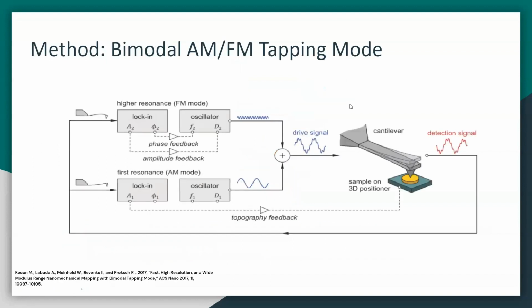So the actual method that I use for the AFM is called bimodal AM/FM tapping mode. And this is shown in the schematic here. It's a fast force mapping mode within the AFM where two resonances are driven at the same time. The first is the higher resonance FM mode, and then the second is the first resonance AM mode. So the topography feedback is driven by amplitude A1 within the first resonance AM mode, and then an oscillation is maintained using a feedback loop.